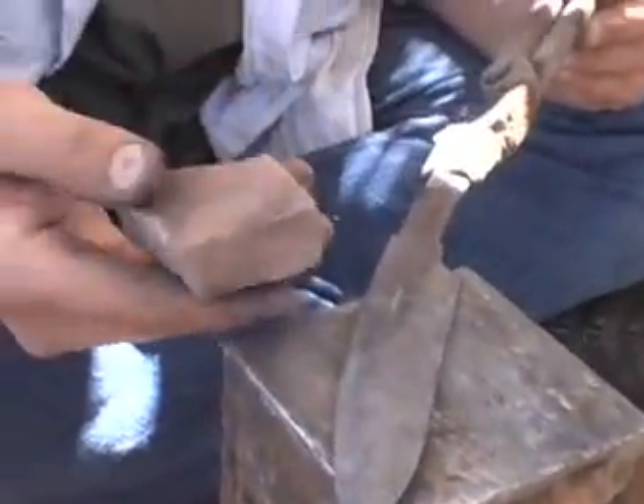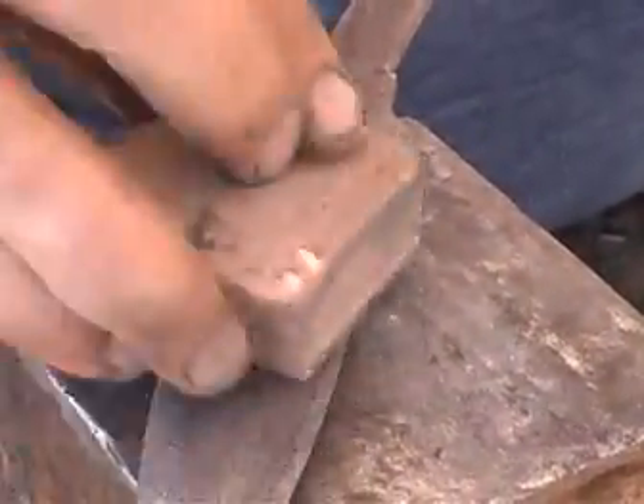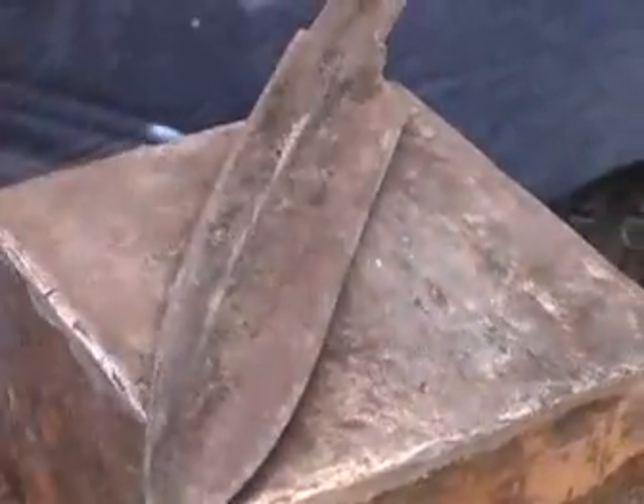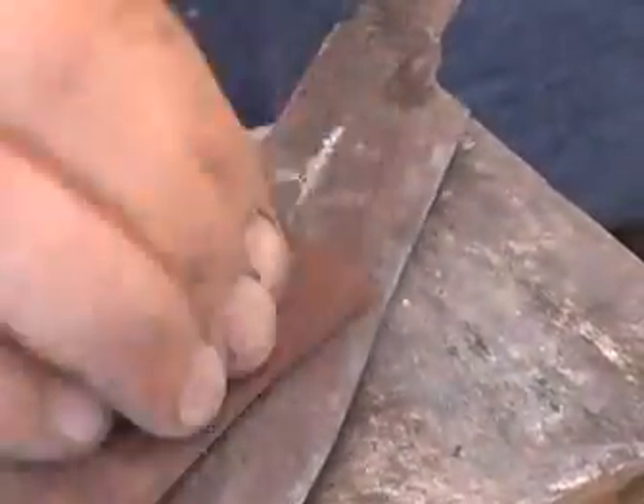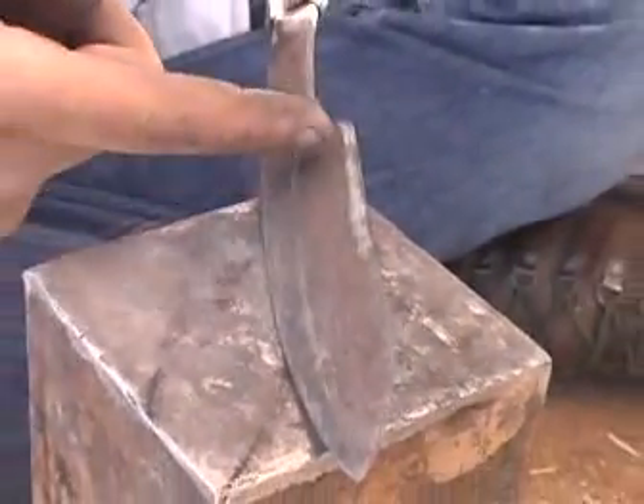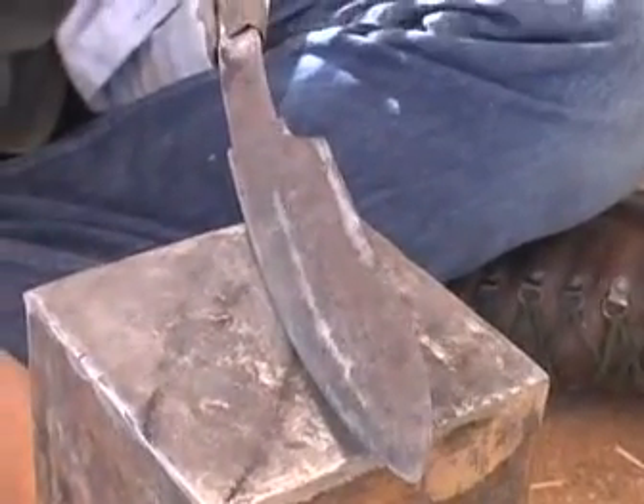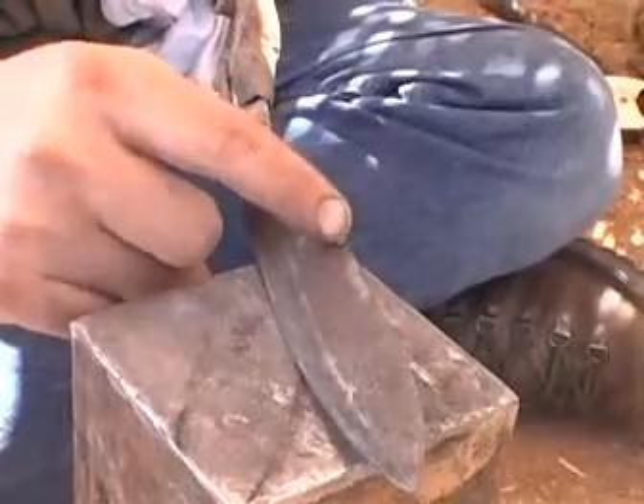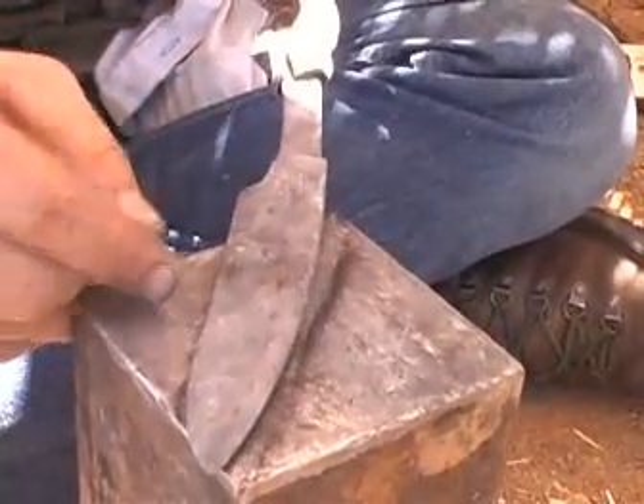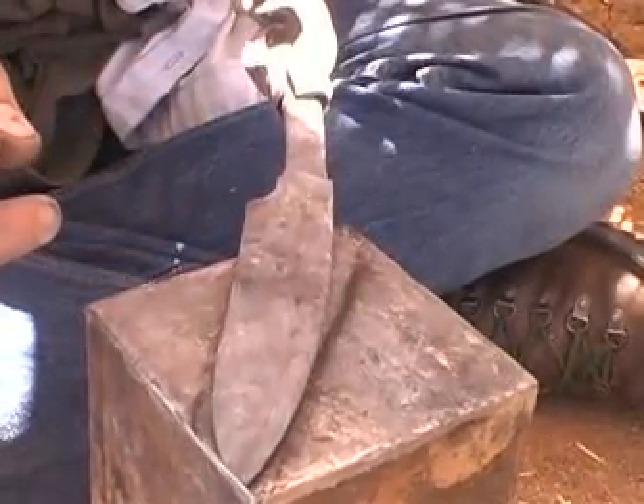I use a little chunk of flagstone or sandstone just to take off the major stubborn spots of scale. And you can see the edge and the ridge starting to pop through all the scale. So now I can just keep going, a little sandpaper, a rock, whatever it takes to get all the little stubborn scale off. You clean it as much as you want to at this stage, and to get the rest of this stubborn scale off, you can soak it in white vinegar. White vinegar will pop all the scale off, but won't hurt the steel. It's about the easiest way to get the scale off that I've seen. You can sand on this for hours. It's real stubborn stuff, but the white vinegar will pop it right off in a matter of hours.